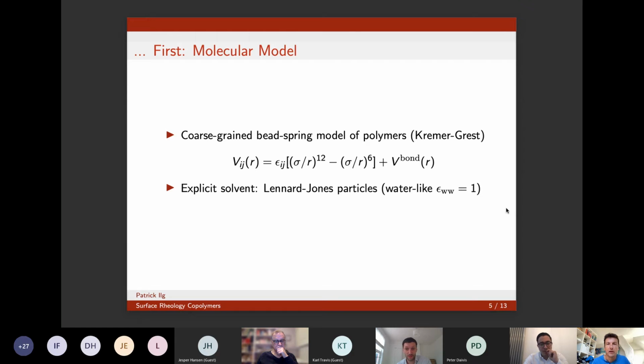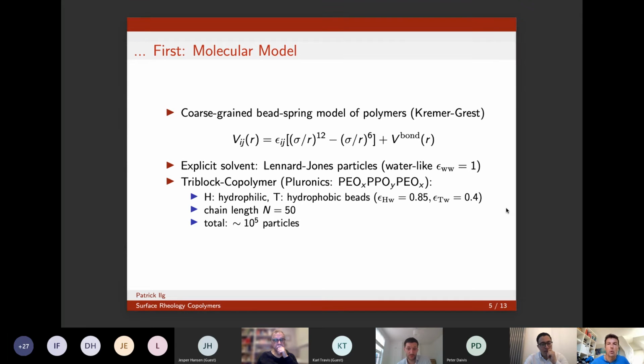In addition, we have explicit solvent, which for simplicity, we take Lennard-Jones like particles, and say they are water-like, which just means our Lennard-Jones interaction parameter is 1. The polymers, the surfactants we are looking at are called pluronics. So they are copolymers, and they are symmetric. They have 3 blocks, one PEO block, then a central block of PPO, and then again PEO. The idea is that both ends are hydrophilic and the central block is hydrophobic. So what you imagine is you have a kind of a hairpin where both ends want to stick into the water.